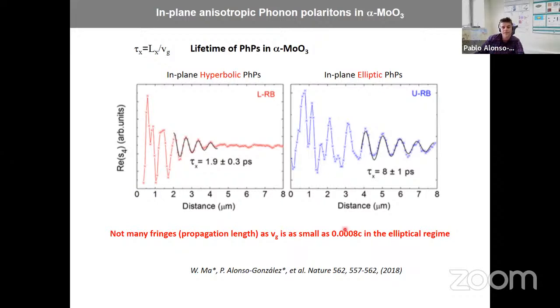This is because the group velocity of this wave is really small. It can be like c over 1,000. So this is a trade-off. If you want something that is really confined, it will propagate slowly, and the other way around. Well, for applications where we want to use this nanolight, where you need a long propagating distance, it's not really good. But on the other hand, if you have a cavity, it lives very long in the cavity. It does not need to propagate very far there. It can go back and forth several times, and then you have a high quality factor for a cavity.